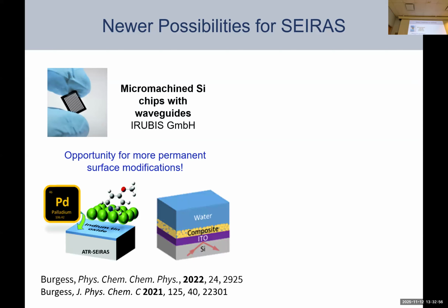So there are a lot of really innovative and exciting developments in this area, and many of them are led by Ian Burgess, who's a colleague in Alberta. So you can see here, for example, that they coat these silicon wafers with indium tin oxide, and then, for example, here with gold, or in this example on the left with palladium. These interfaces are a little bit better than direct metal onto silicon, which often have really poor adhesion. And there's additional developments in this space that I'm not mentioning here that I'm also happy to talk about.